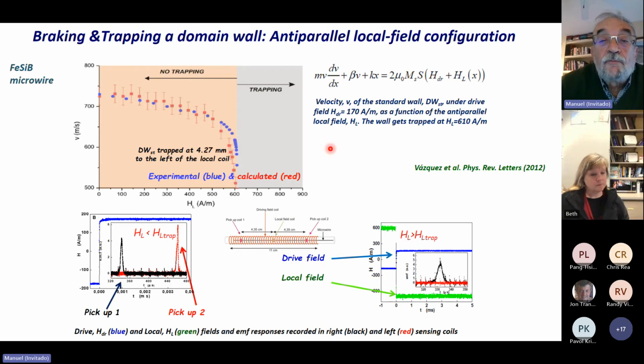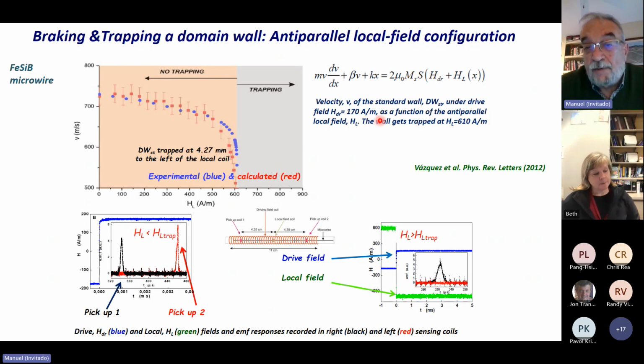So in this plot, you see this is the experimental value of the velocity of the domain wall. It's a maximum of around 730 meters per second when we have no local coil. But as we apply the local field coil, we can control the velocity of this domain wall. We can decrease its value, and eventually we can stop the position of the wall in a given position. And this position depends on the amplitude of the local field, also considering the particular value of the driving field. This case was 170 amperes per meter.